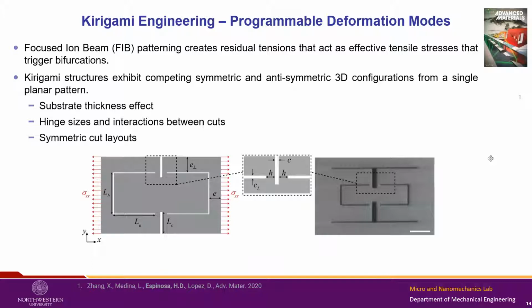So the first work that we conducted in the group was, interestingly, at the micro-nanoscale, where we used focused ion beam patterning that created some residual tensions in the substrate, which is a silicon nitride substrate. This created residual stresses that caused the material to bifurcate without actually applying any tension, so not controllable. You just do the FIB patterning, and that generates the natural emergence of this Kirigami phenomenon.